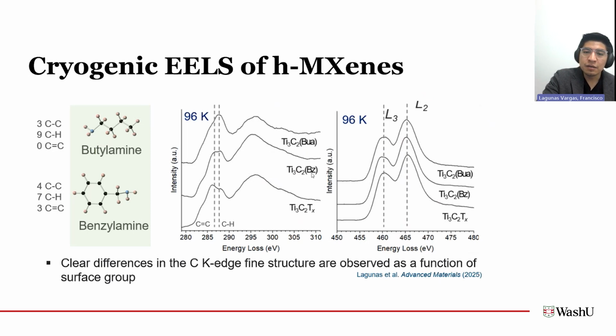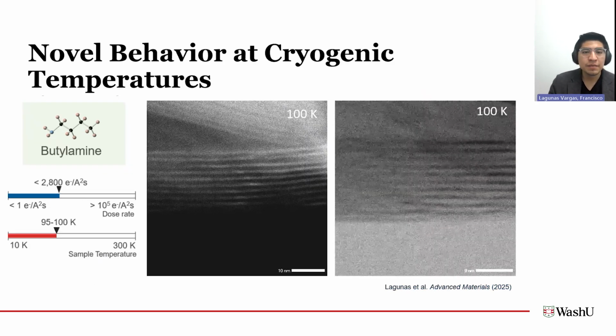So here is our benzylamine terminated MXene and our BUA terminated MXene. And you can see between this 285 and 287 region, this profile is a lot more flat compared to the BUA sample. And we suspect that arises due to the differences in the carbon double bonding and the carbon-hydrogen bonding present in each of these materials. So that's really exciting. We're seeing directly signatures of the organic material.